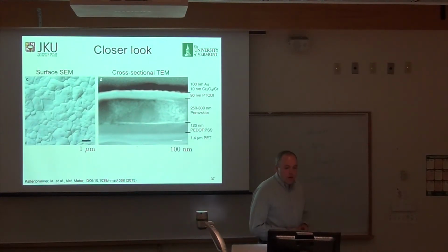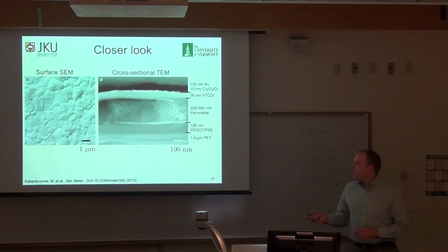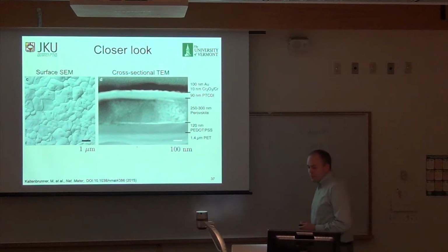Taking a closer look, we can see an SEM image of the surface of the perovskite. We see that we do have microcrystals, but they are pretty compact, with no real holes in between them. And if we do a cross-sectional TEM, we can see the thicknesses of the respective layers, so they're all there.